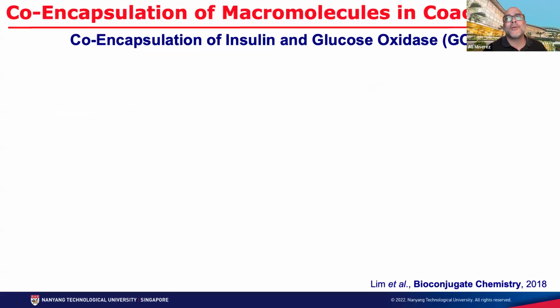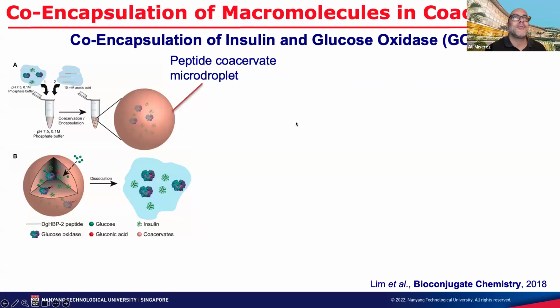And so when we first studied this a few years ago, as a first proof of principle, we were interested in showing that therapeutic can be recruited within the droplet, and then the droplet can be disassembled by an external stimuli. We just wanted to see, can we do that? And so we started by encapsulating insulin and glucose oxidase inside those droplets spontaneously, as I showed you earlier. And then when you flow glucose, because you have glucose oxidase here, it will become gluconic acid. So it will acidify the inside of this droplet. And when it's acidic, the droplet disassembles and releases the insulin on demand, basically according to glucose level. So that was just a proof of principle.